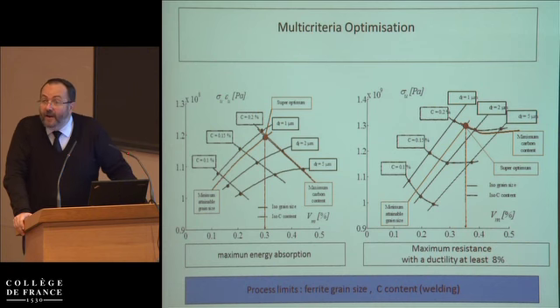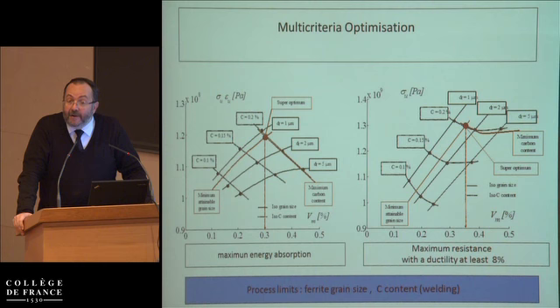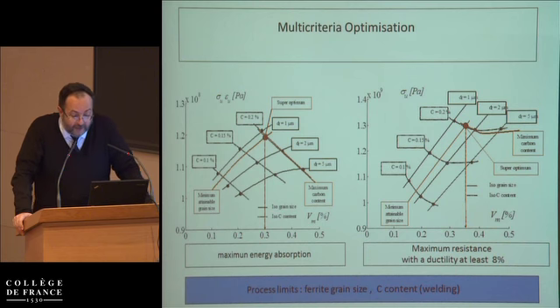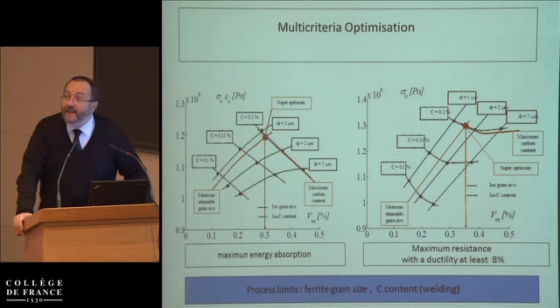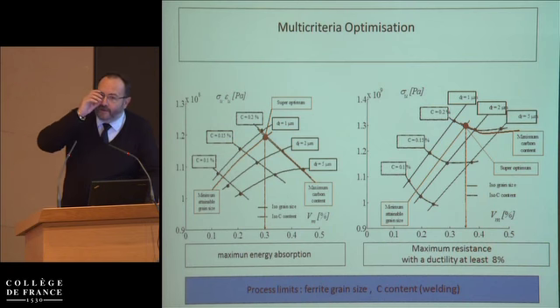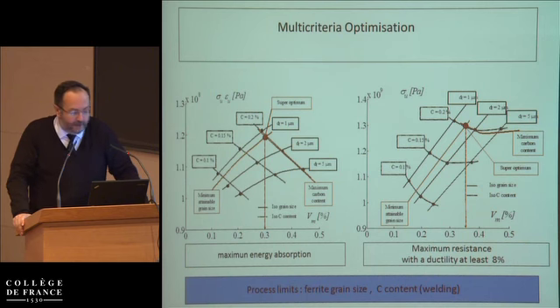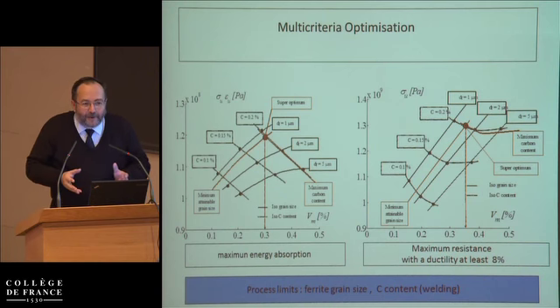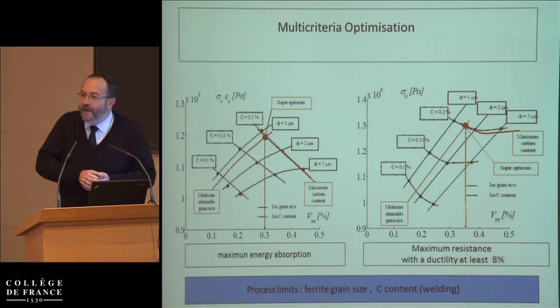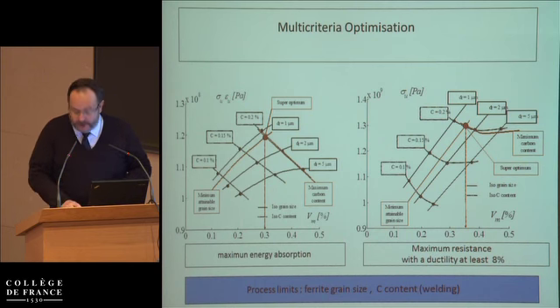So that's coming from micromechanics modeling of the behavior of the ferrite plus martensite mixture, and the ferrite behavior depends also on the ferrite grain size. And what you can find is that depending if you want a maximum energy absorption or if you want a maximum resistance with a ductility which is at least 8%, which are typical requirements for this kind of materials, this kind of modeling is going to give you the best carbon content, the best volume fraction of martensite, and the best grain size in ferrite. So you see what we have done here is designing a material which is tailored in order to meet a requirement which would be difficult if we didn't have this mixture effect.